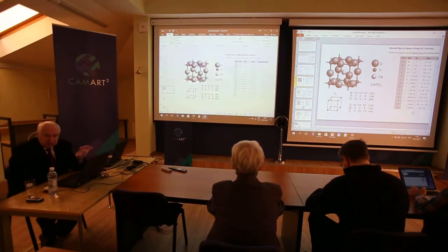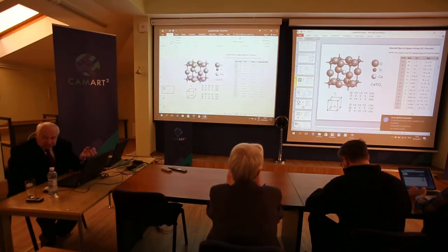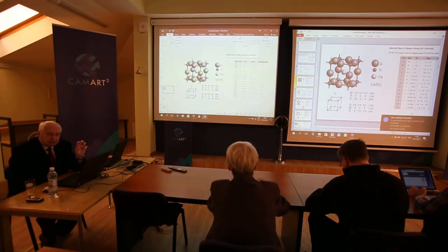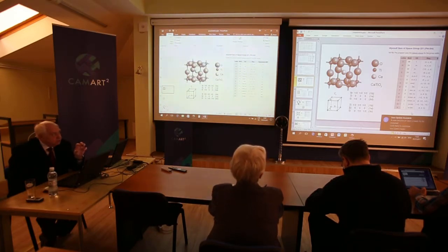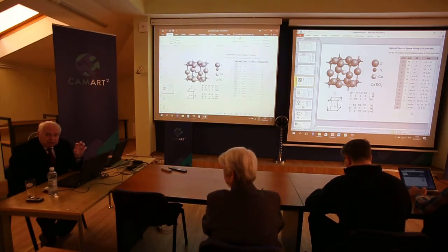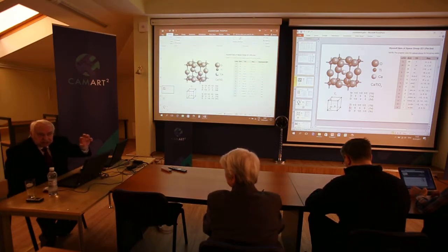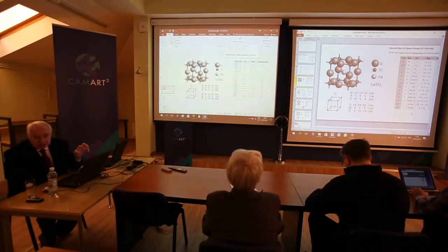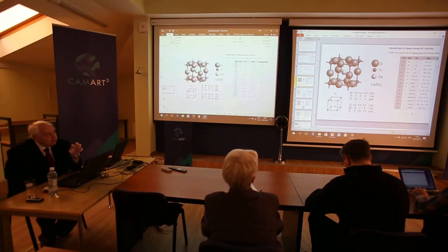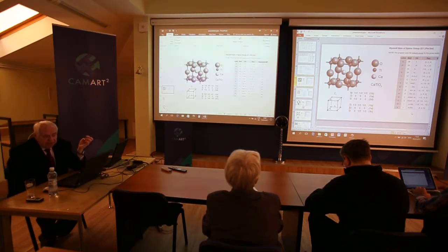Each space group consists of a part connected with the lattice, and the smallest volume in the lattice is the primitive unit cell, which is translated over the crystalline space. In the case of perovskite, a simple cubic lattice with one parameter and 5 atoms in the primitive unit cell.